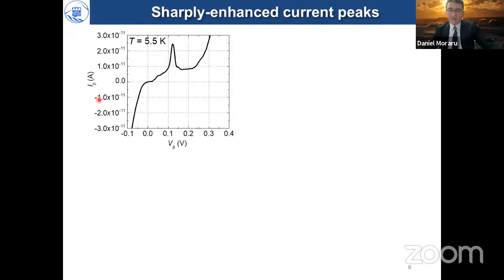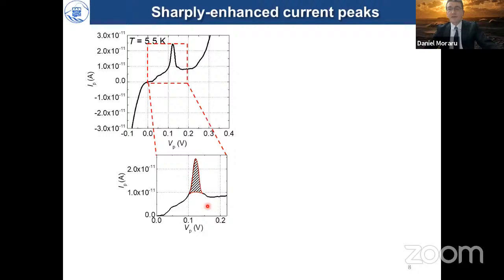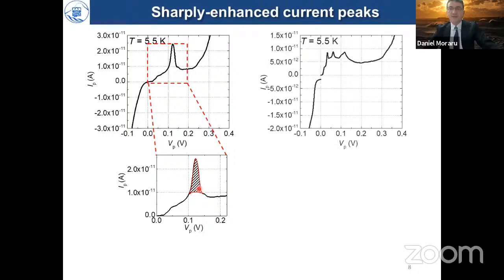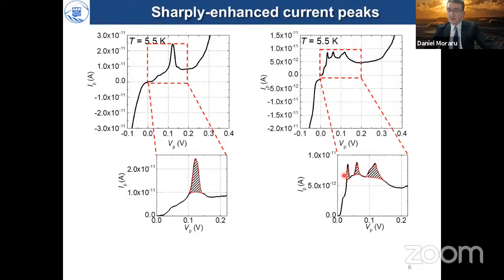So the first observation that we obtained that was quite interesting for us was that of sharply enhanced current peaks. What I'm showing here is the low temperature IP-VP characteristics of some devices. You can notice the relatively high reverse bias current, and also the NDC characteristics in the forward bias, as well as the typical PN diode characteristics. What is most peculiar here is actually this locally enhanced current peak illustrated here. In other devices, we obtain multiple such peaks, not only one, so we observe several enhancements locally in different positions in VP.